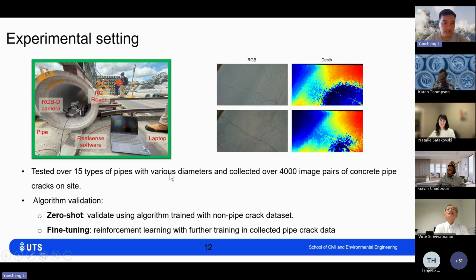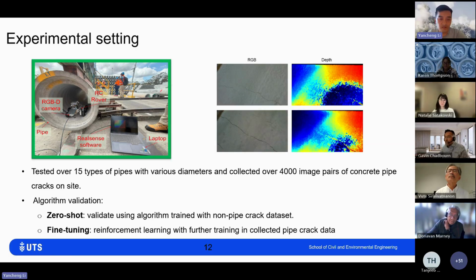We tested over 15 types of pipes with different diameters and collected over 4,000 image pairs of concrete pipe on site. For algorithm validation, we did two steps. The first is zero-shot, because we also did other research on other types of concrete defects. Typically that concrete crack is wider, not as thin as 0.1, 0.15 or 0.3, probably at the millimeter level. So we tested training only on that data set, which is not related to thin cracks, to see how it works.